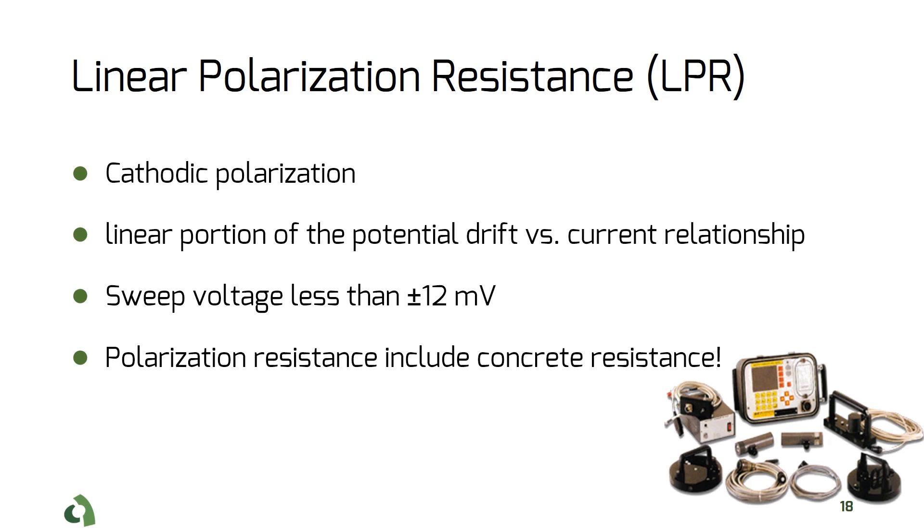It is generally suggested the sweep should not go beyond plus-minus 12 millivolts on both sides of the open circuit potential. Otherwise, the linearity of the relationship cannot be assured. It is worth noting that the polarization resistance measured by this technique includes the concrete resistance.